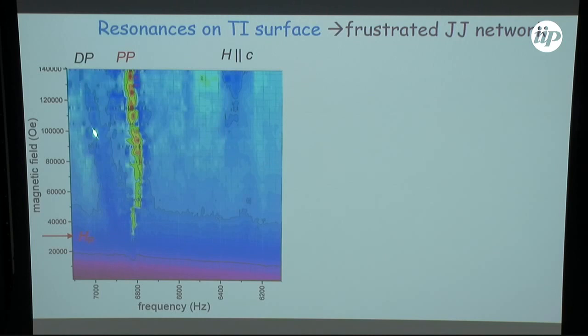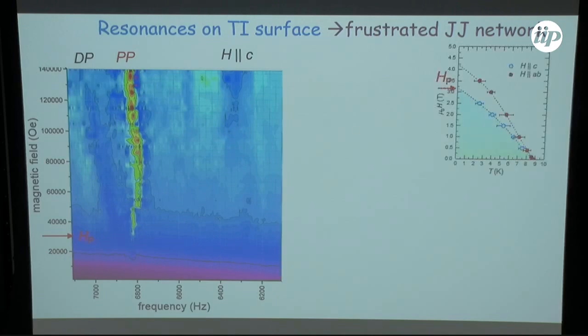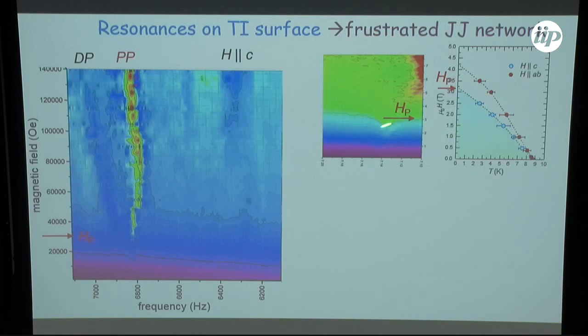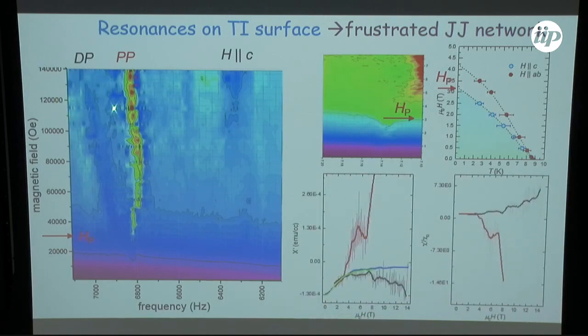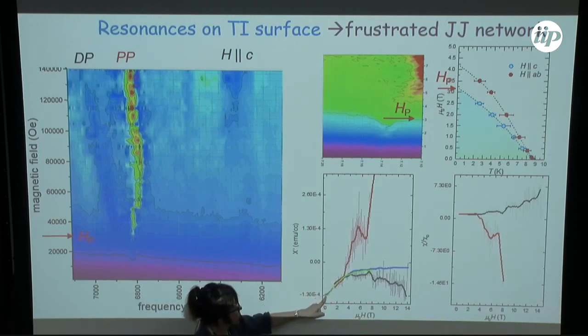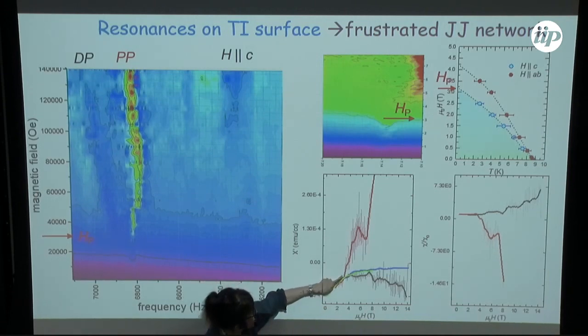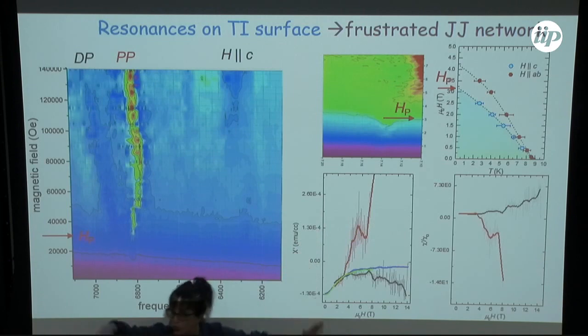This disperses, like so. And this paramagnetic peak actually sits in a diamagnetic trough. And they're kind of dancing with each other. I'll show you this in a moment. This is actually quite interesting. And again, this all starts around here. And in fact, there are some interesting features at lower fields, which I cannot discuss here. Now, these 3 features, and off resonance, it's what I showed before. If you look at chi prime as a function of field, all this susceptibility behaves just like what we've discussed before until you get to this paramagnetic limiting field, and then it's hugely enhanced on this paramagnetic peak, okay, and depressed on the diamagnetic peak.